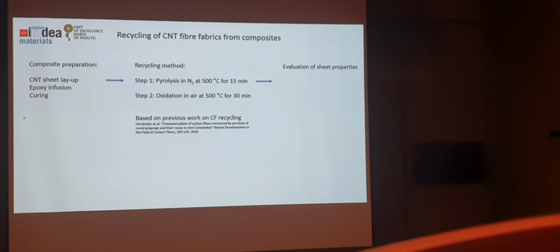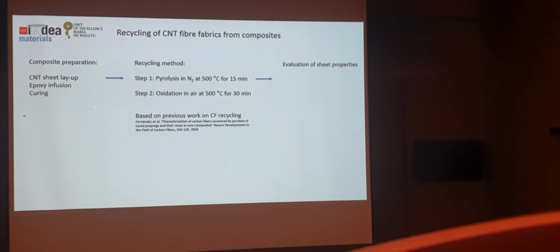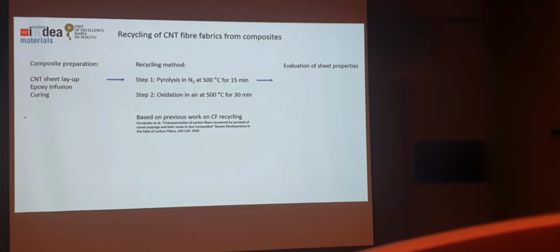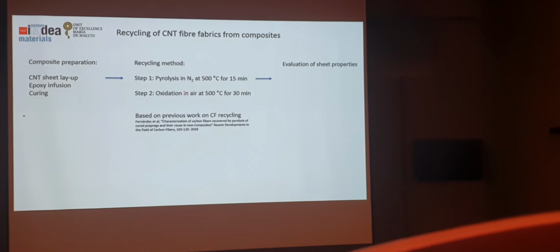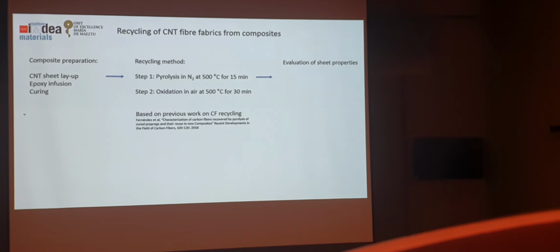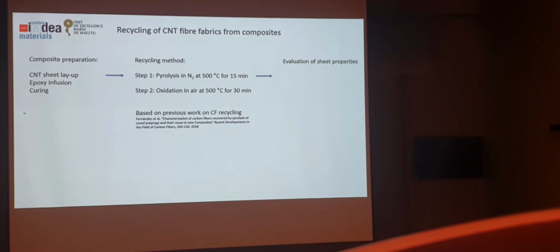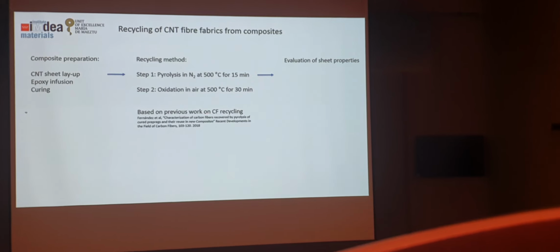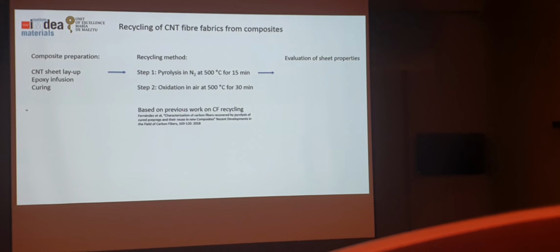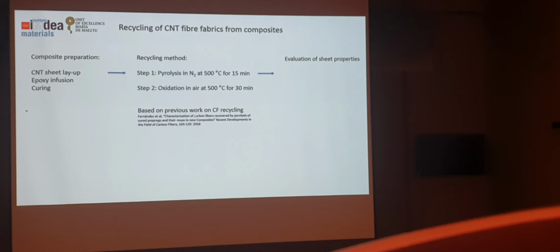And so the idea is we make a composite, and to study recycling potential, we produce these composites, we cure them, then we pyrolyze the matrix, oxidize it slightly, and then evaluate the properties. Now, of course, you could recycle in many other ways, and I'm sure there are many better ways of extracting the polymer. We didn't do it because our interest was in understanding how the CNTs survive the process. And this recipe, I suspect, could be improved significantly. We just took it from some colleagues who are working on recycling carbon fibers.